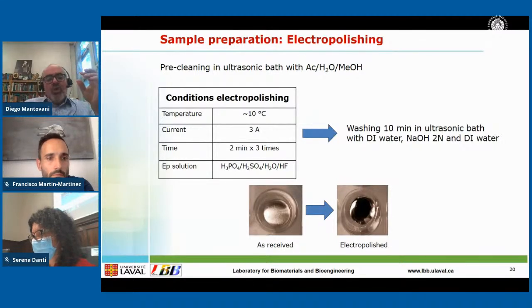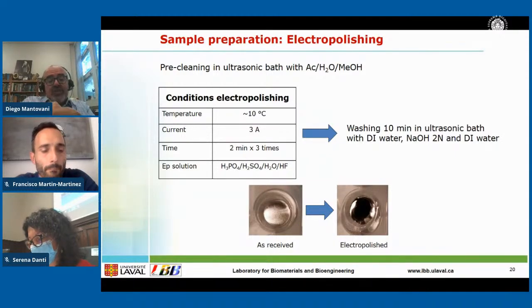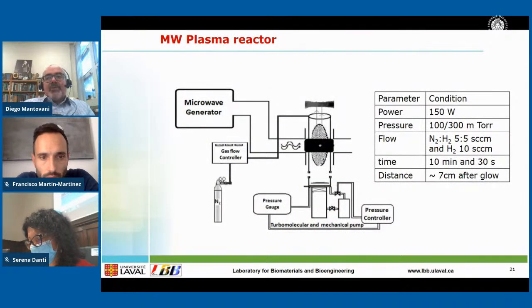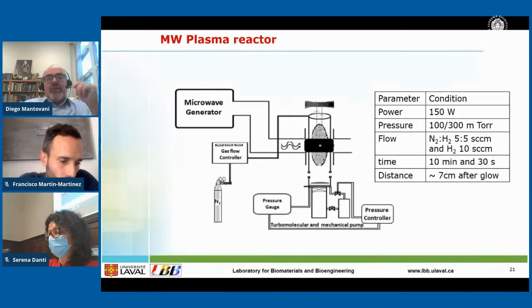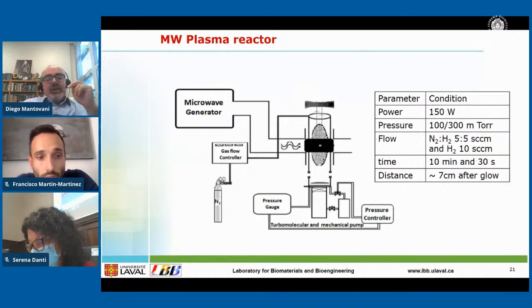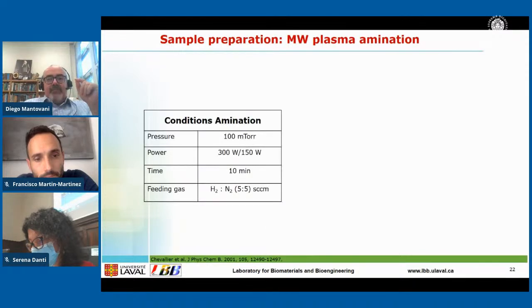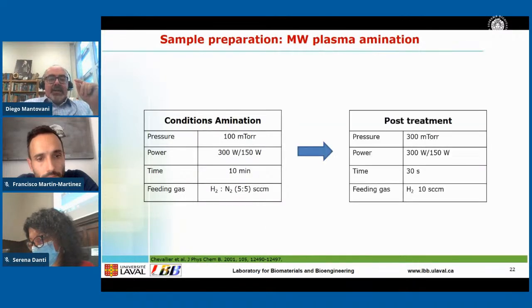One should know that the stents for cardiac, vascular, and neurological application are generally surface treated in order to get a roughness of 4 to 6 nanometers. So the plasma reactor is this one. The proof of feasibility was done in a conventional plasma reactor, and then a more targeted plasma reactor was developed where 18 stents can be positioned inside.